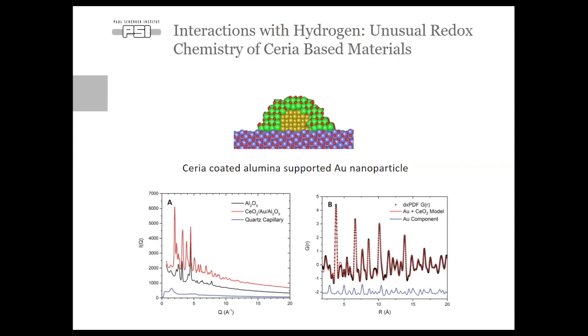So, at each different temperature point, we ran a blank experiment, which was just an alumina support, and one which was our real sample, and then we subtract the relevant alumina support from the material to the Fourier transform, and we arrive at the pair distribution function on the right. So, this actually contains two different structures. You have the scattering from the cerium, and the scattering from the gold component. But the gold component here is still very weak, although discernible. In particular, we see the gold-gold scattering quite clearly at the first and third major points in the lattice, so 2.76 angstrom and just under 5 angstrom.